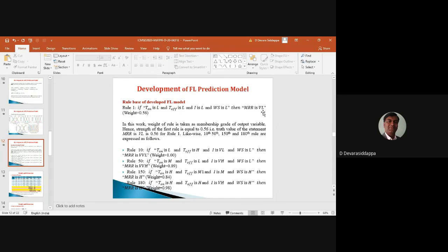But here we have taken the membership grade of the MRR response variable as the weight, meaning the truth value of the statement. The rule reads like this: if T on is low, T off is also low, current is also low and wire speed is also low, then the truth value of MRR being very low is 0.56, which is equal to the membership grade of the predicted MRR value. Like that, we have correlated all the rules starting from 1 to 180, and some of the rules, the 10th, 50th and 150th rules, are given here with the respective weights assigned to the rule.